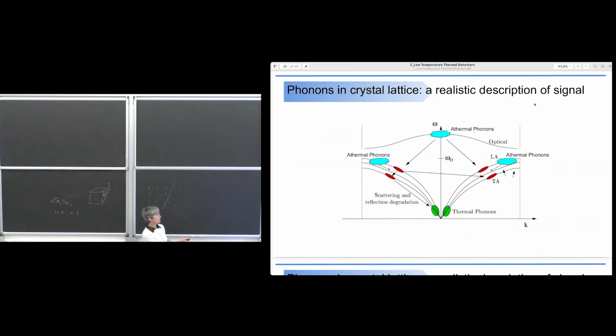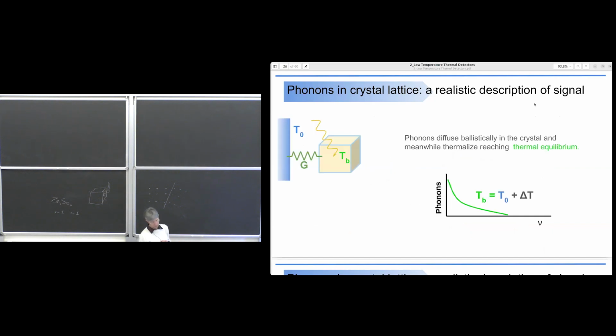This is a picture that illustrates what happens. You have this cloud of athermal phonons, and during thermalization, optical athermal phonons are transformed into the acoustic branch, and then they are degraded to thermal phonons. So after some time, your peak of phonons is moved toward the thermal distribution, and you achieve thermal equilibrium with a distribution that corresponds to an increased temperature.